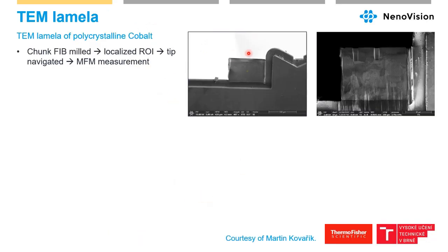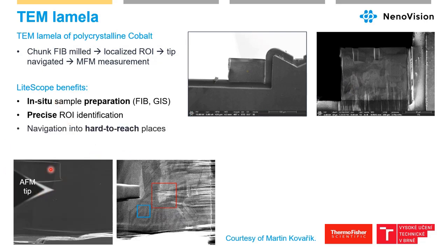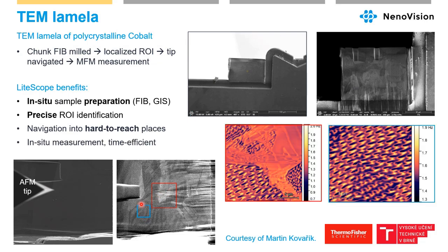And so here is another example of polycrystalline cobalt. We see the lamella here. First, the chunk was FIB-milled, then we localized the area of interest, and then navigated using the tip. So as we have the navigation here, we have the area of interest. In backscattered electrons, we see two structures which we'd like to measure in MFM. And we see how the structure actually looks. So it was quite surprising what we saw.